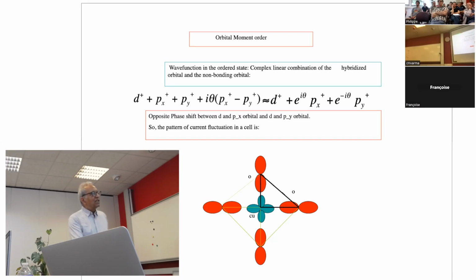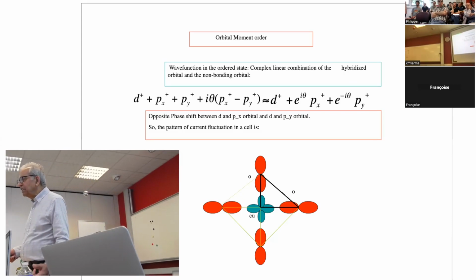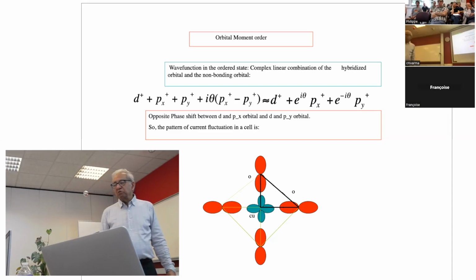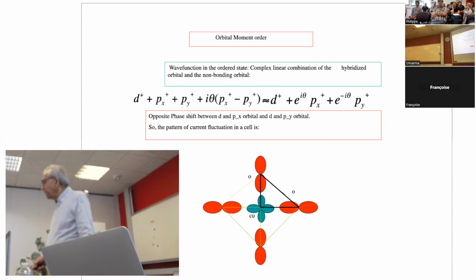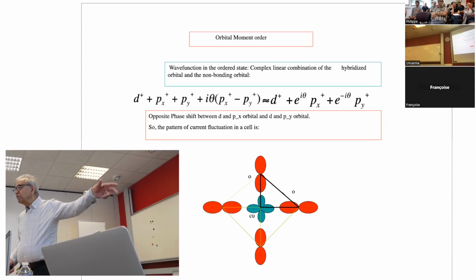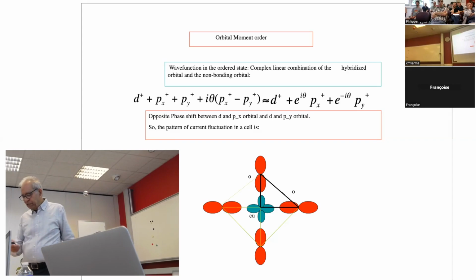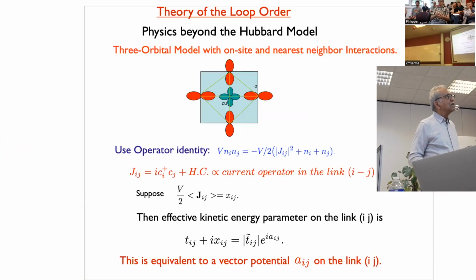Now, it turns out there are lots of ways, three different ways of closing the loops. And I, of course, picked the wrong one first, and then finally settled on this one based on the first experiments that came out, in which current is flowing from here to here to here, and it's flowing from here to here. So there's a clockwise loop and an anti-clockwise loop, but you can see that there are four possible domains of this. Okay, and those four possible domains will play an important role in the story.